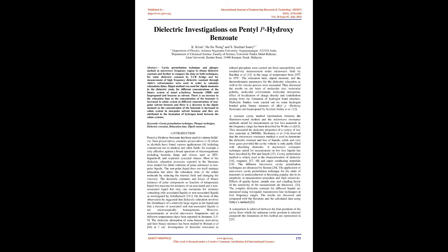There is an increase in the relaxation time as the concentration of the benzoate is increased in the solute system in different concentrations of nonpolar solvent benzene, and there is a decrease in the dipole moment as the concentration of the benzoate is increased in the solute system in nonpolar solvent benzene. They are attributed to the formation of hydrogen bonds between the solute systems. Keywords: cavity perturbation technique, plunger technique, dielectric constant, relaxation time, dipole moment.